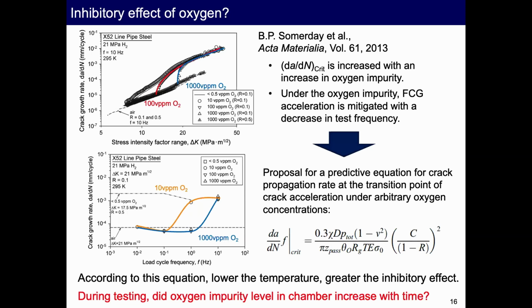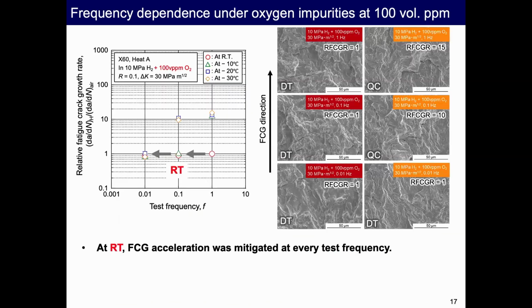Under oxygen impurity, the crack growth acceleration is mitigated with a decreased test frequency. Based on physical modeling, they proposed this kind of equation. But according to this equation, the lower the temperature, the greater the inhibitory effect. So firstly, we considered the possibility that the oxygen impurity level in the chamber increased with time during the testing. We always think about it. To confirm this tendency, we performed additional testing.